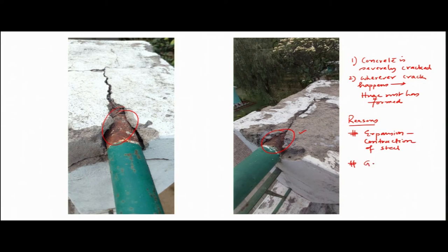But the second part is leading to a kind of galvanic effect of corrosion. Now, let us analyze why the galvanic effect. If you see that outside is painted, the paint is not an impervious thing. There are pores, and it can also have mechanical damage over the years. It does not happen in 1 month, 2 months, it will happen after 1 year or so. So, at those cracks or breaks in the paint we have exposure, and there we have moisture as well as oxygen.